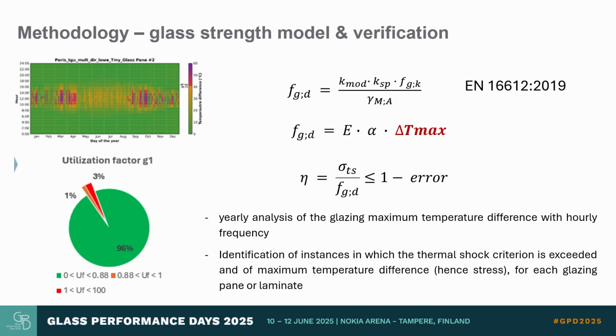This calculation is done for every glass pane of an IGU, and then we are eventually producing a carpet plot for a certain pane of the IGU, in which we see the temperature all over the year, but eventually the delta T and then the stresses. And this is basically the amount of time during a year my utilization factor is below 1 minus the safety margin that we want to take, or eventually in a risky area, or if there is a red, it's a failure. So whether we are in yellow or red, we won't pass the thermal shock analysis.